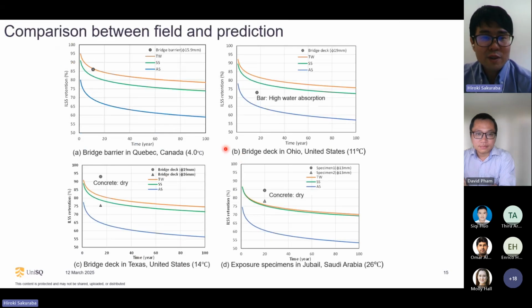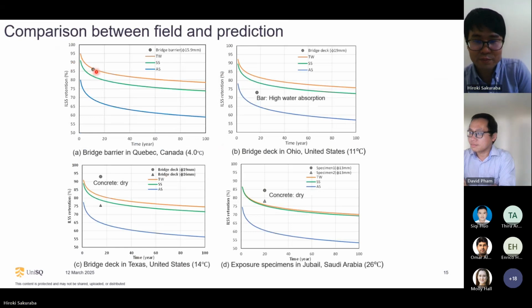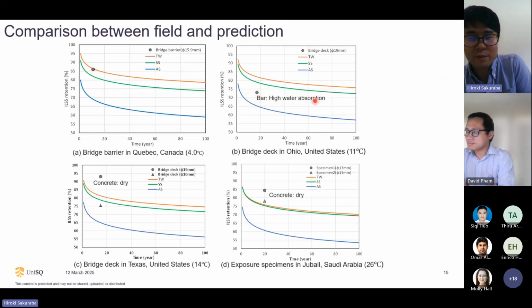This is a comparison between field durability test data and the prediction data. For example, in figure A, this is the field durability investigation data. This really agrees well with the prediction result. For this prediction, this has a relatively low retention. This is because this bar has higher water absorption. So I believe that's why this had a relatively low retention.